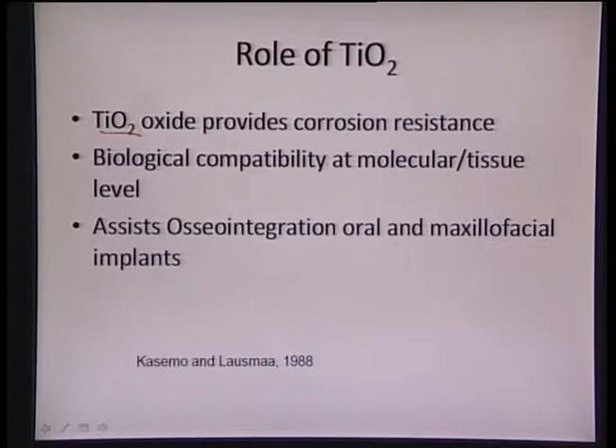And the corrosion resistance comes in the titanium alloy because of the presence of this titanium oxide layer. So the titanium oxide layer acts as a barrier for the surface to interact with the titanium implant, and this titanium oxide is responsible for rendering the corrosion resistance at the tissue level. Because of its similarity, it can allow the cells or tissues to grow on its surface without inducing any toxic effects. So that biological compatibility is available even at molecular scale or even at the tissue level, so that tissues find a very friendly environment on the titanium oxide surface, because it is no more titanium. Titanium is basically covered with an impervious layer of titanium oxide.